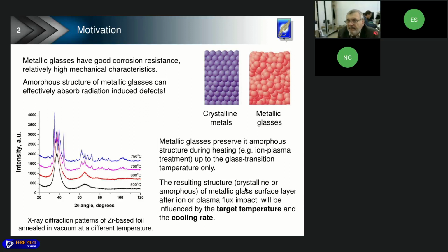Thus, the resulting structure, whether it will be disordered or crystalline, will be influenced by the cooling rate after ion or plasma flux input. This cooling rate will of course depend on material type and radiation characteristics. In any case, if the cooling rate after high temperature plasma input is higher than the critical rate necessary to preserve amorphous structure, then one could expect that the glass structure will be stable under plasma effect. It preserves its disordered structure. For example, earlier investigations showed that treatment of iron-based metallic glass by high-intensity pulsed ion beam didn't change its disordered structure.